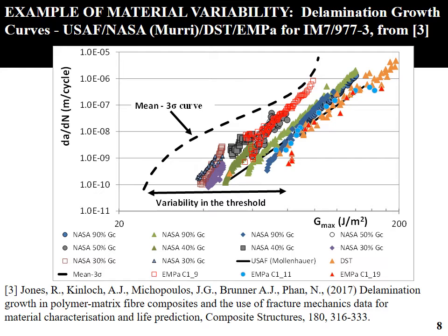Each one of these curves can be accurately captured by the Hartman-Schijve equation that we've mentioned, and consequently, we can determine the variability both in the threshold and in the toughness. This enables us to determine the worst case, the mean minus 3 sigma crack growth curve that you need for your assessment.